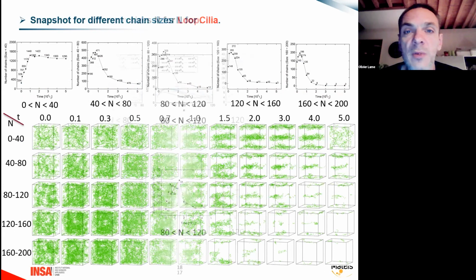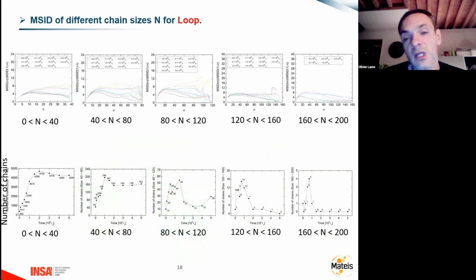And just to see that we can have much information about this system, we perform the same for the loops. I will begin with the number, which is quite comparable to cilia. There are a lot of very short loops, and from 40 to 80 is quite significant too, and then it decreases for the very long loops after the end of crystallization.